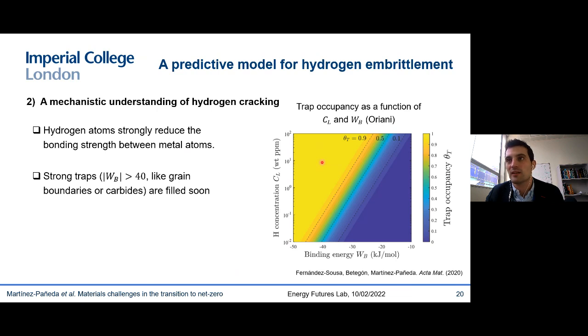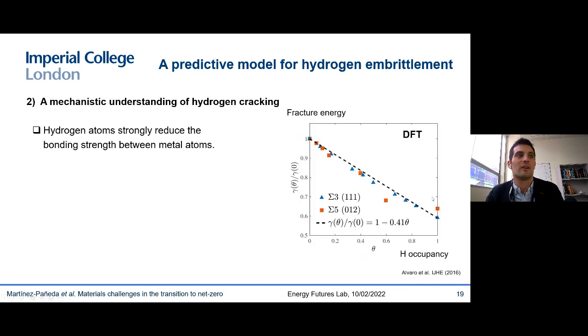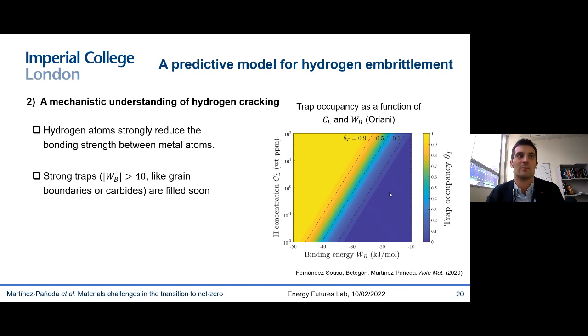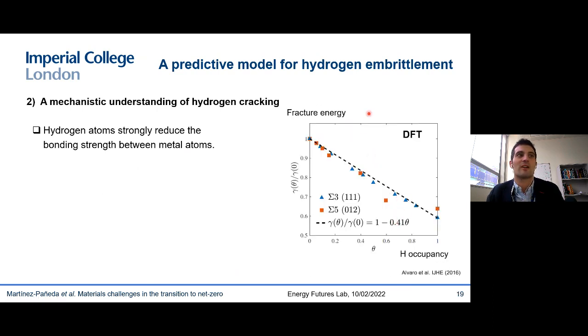And this can play in two ways. If you have, for example, failure occurring at your grain boundaries, and you believe that your mechanistic interpretation of what's happening in hydrogen embrittlement is that the decohesion process is happening at the grain boundary, then it's important to know the binding energy of those grains, depending on the grain characteristics, because that will tell you for a given environment, a given hydrogen content, how full your grain boundary is. And then you will come here and you will see how much it has been degraded, basically. What is the fracture energy or the surface energy degradation with the hydrogen content?